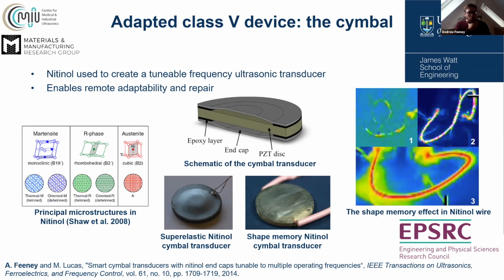Now, the physical properties affect the transformation temperatures of a material such as nitinol. So does the composition of the material and how the material is fabricated. Now, why would we necessarily want a device like this to exhibit tunability between two frequencies? Well, different frequencies, for example, might be very useful for efficient operation in a surgical process, between hard and soft tissues. If you're penetrating soft tissue first and then bone, the operating frequencies for efficient cutting processes can actually be quite different. And it's been shown in the literature. Softer tissues, for example, typically benefit from a higher operating frequency for cutting compared to those for hard tissue. So that would be one immediate example that I could think of.